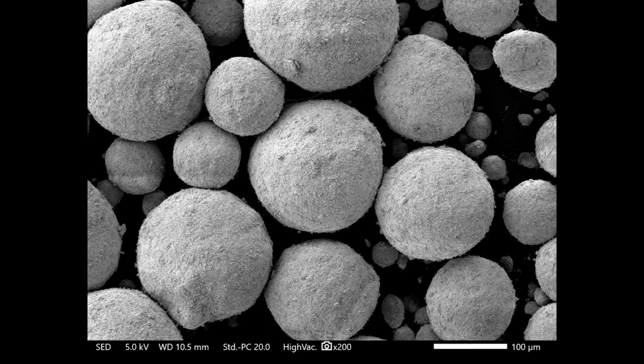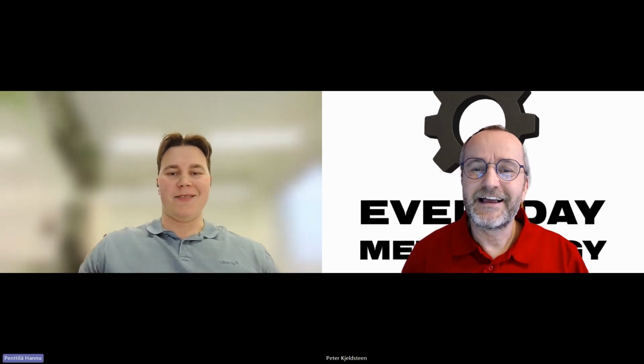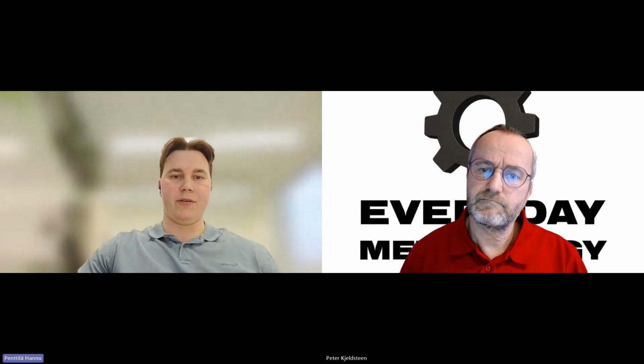The dusting leads to the question that there's cobalt in the powder, and cobalt below 5 micron, is that a risk? I'd say at least at some level, yes, of course. Especially with cobalt-containing fine powders, it's considered toxic when inhaled. And you know that in the industrial settings, the exposure to these cobalt powders is monitored in some way, but there are luckily some ways to reduce these risks with some proper safety measures.